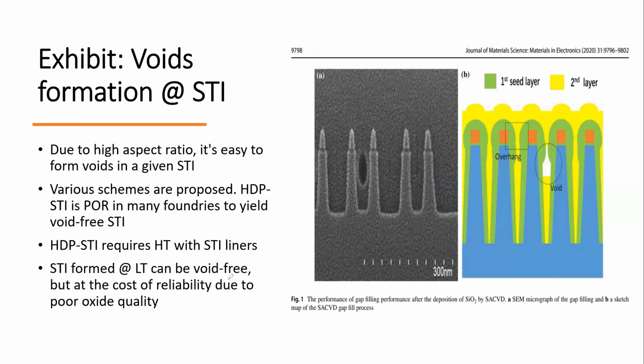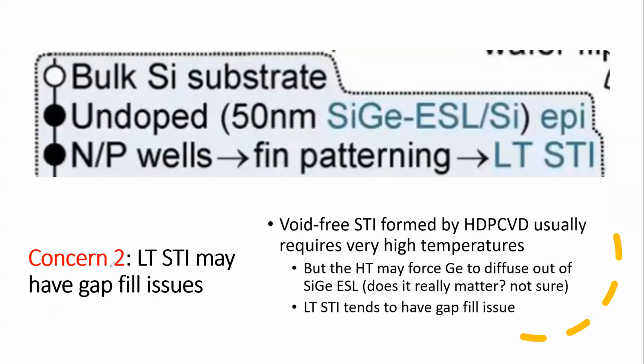So it can be void-free. It's okay initially, no voids, but later on you develop problems. So the low temperature STI could give you some headaches. So that's one concern I put down too. STI may or may not have a gap fill issue, but it will have the reliability issue. So all these are problems that you need to be worried about.